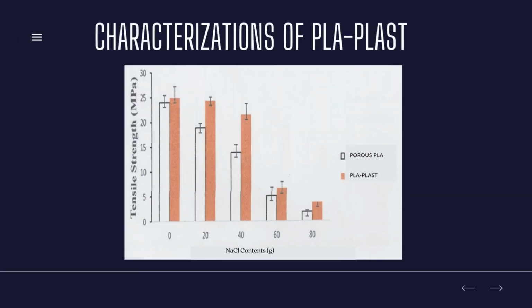Characterization of PLA+. The effect of NaCl content on tensile strength of porous PLA and PLA plus show that the decrease in tensile strength when the NaCl content increased. The tensile strength of PLA plus was higher than porous PLA due to the effect of PDMS as toughening agent.